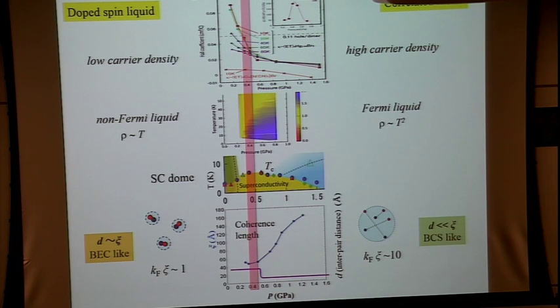But in this doped spin liquid region, coherence length is diminished, and the Cooper pair distance, the average distance, is increased, and they are nearly the same. So overlapping is small. So I think that in these materials, as a function of pressure, the BCS to BEC crossover occurs. This is an additional interesting aspect of this doped spin liquid superconductor.